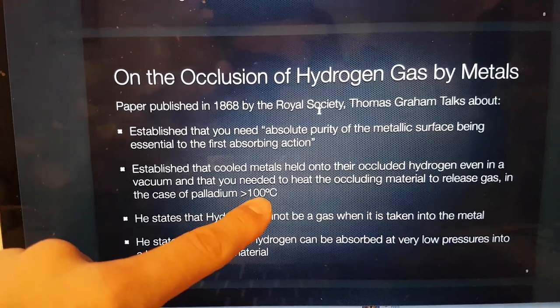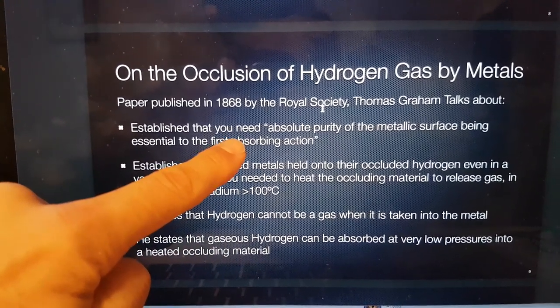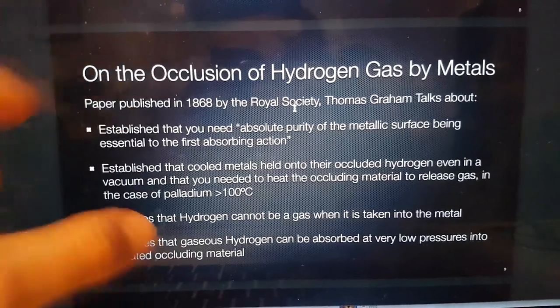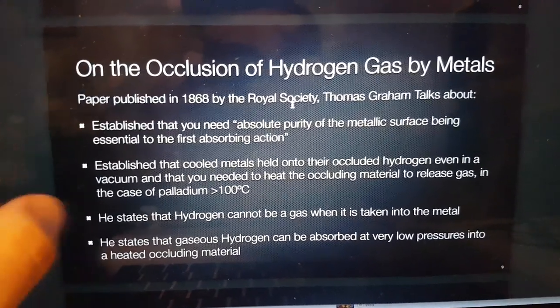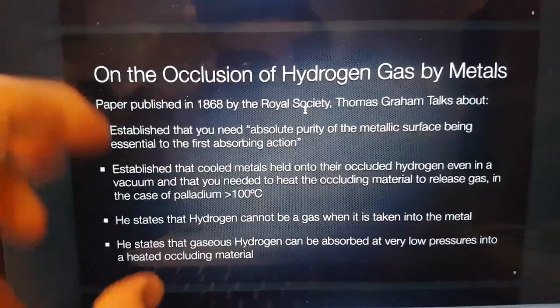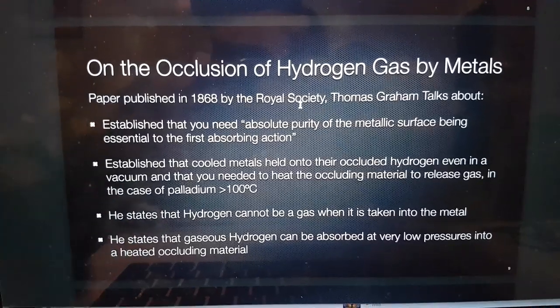And in the case of palladium, you have to have first the material cleaned, and this is what Parkhomov is talking about, by firstly baking out at a lower temperature to get rid of nitrogen and other volatiles that might be on there. You don't want to set those permanently in place and cause a problem before you start trying to get rid of the oxides and putting hydrogen in. And once you've got rid of those in deep vacuum, then you're loading, putting hydrogen in to reduce the oxygen, take it out as water, and repeat that a number of cycles.